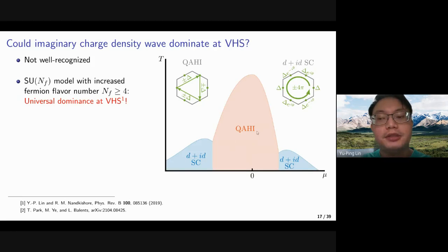the imaginary charge density wave will be a universal leading instability at the Van Hove singularity, and it realized a quantum anomalous Hall insulator, or you can say the Chern insulator. And if we dope it away, it will go into the chiral superconductivity, which was leading for graphene.